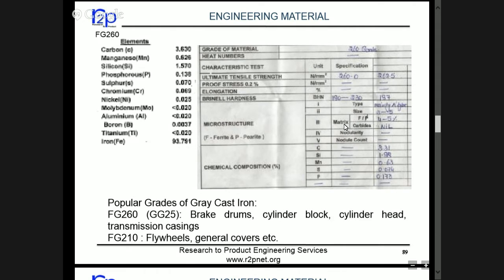Another thing you see in this sheet, which is cast iron tested in a laboratory: the microstructure consists of ferrite and pearlite, right? Ferrite is not good, you can say, for the lower grade castings. Ferrite is there, but in good grade casting, pearlite is desired. So ferrite should be below, like here it's written 4 to 5%. Ferrite will make the structure weaker, and at high temperature it will just break down. The component itself may break down. So desired is to have minimum ferrite and more pearlitic structure.